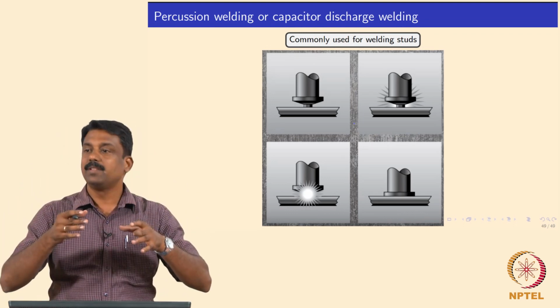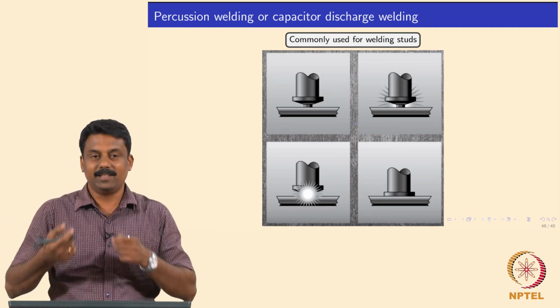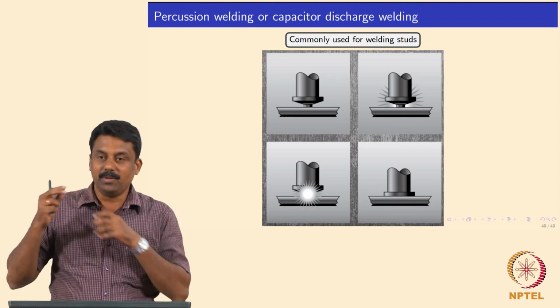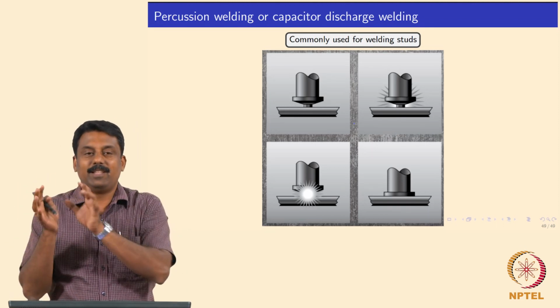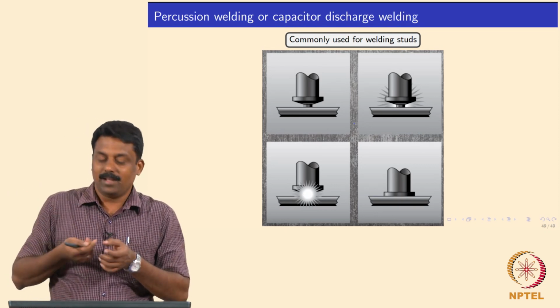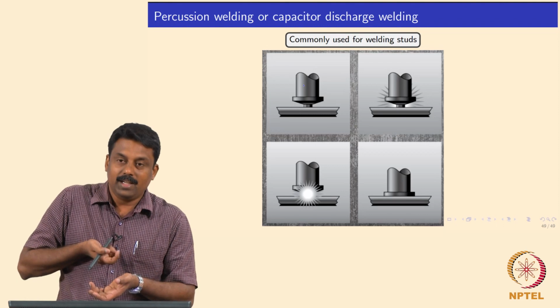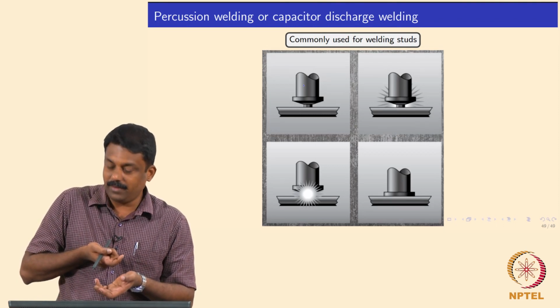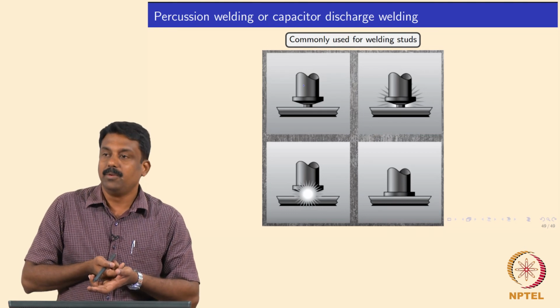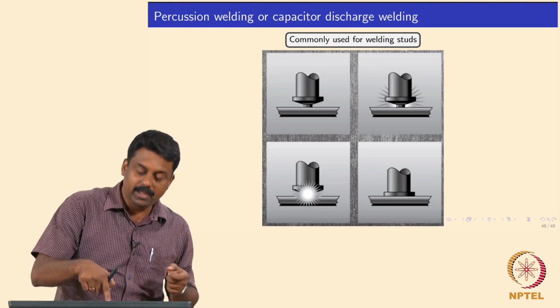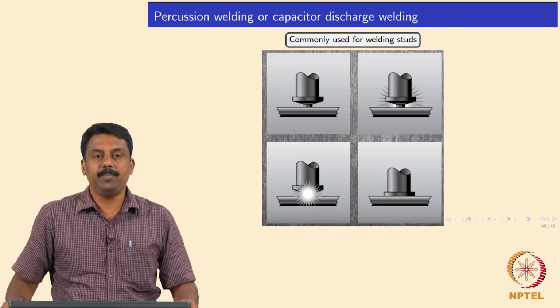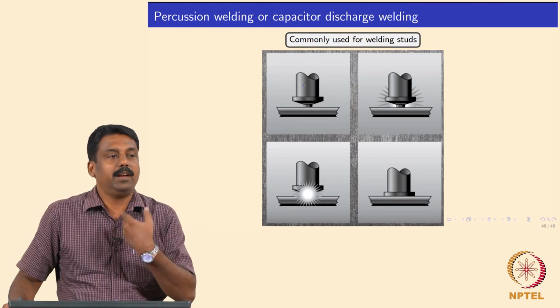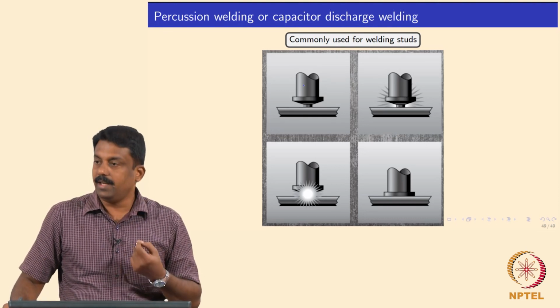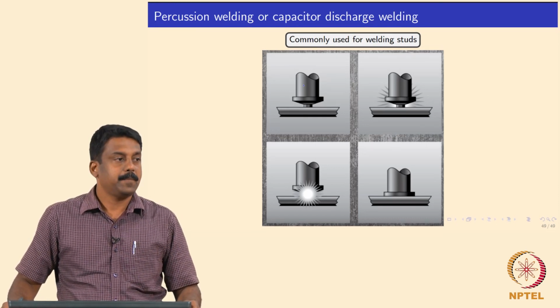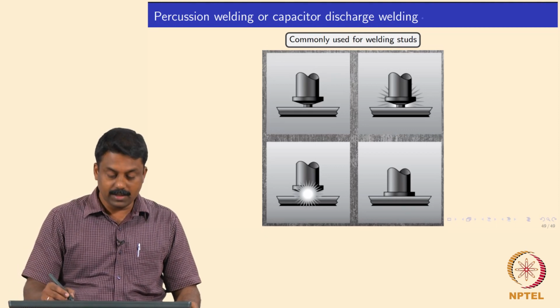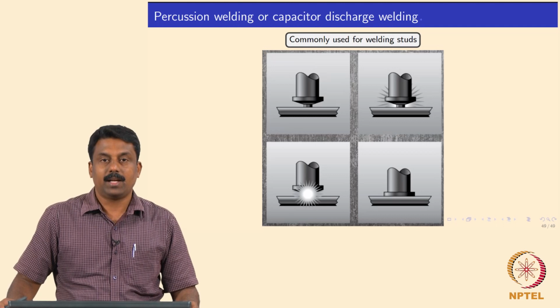So there will be one robot with a gun. This can also be done with a hand gun as well. You fill it with a bullet, which are now studs or bolts, and then you bring it in contact, something like this, and press the trigger, you discharge the current at the interface. Simultaneously you also use an air gun or something like that. The stud will be going towards the piece. The moment you have a contact, the electric current is discharged, and you melt the interface and form a solid joint. So this is commonly known as percussion welding, or capacitor discharge welding.